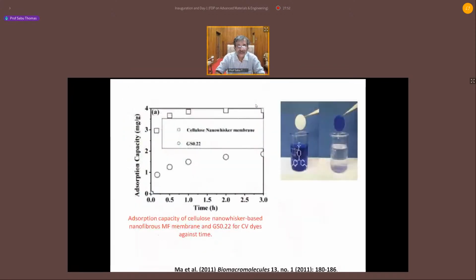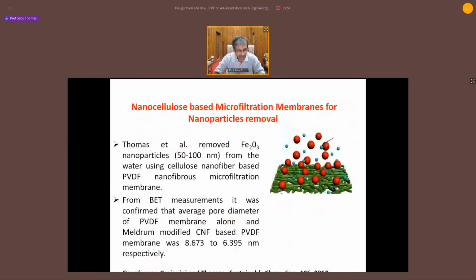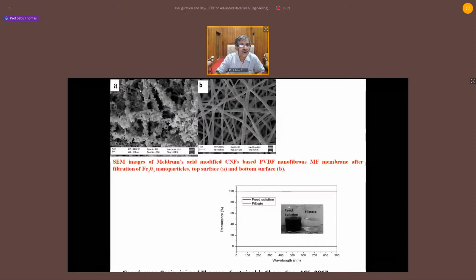Now let me show you another important slide where my PhD student and I worked together and found that this filter is extremely beneficial to remove suspended particles in water. You know, water has a lot of suspended particles. Look at these, they are all iron oxide particles, metallic particles. And when we filtered this water having lots of suspended particles, you see, all the suspended particles were retained at the top of the filter.